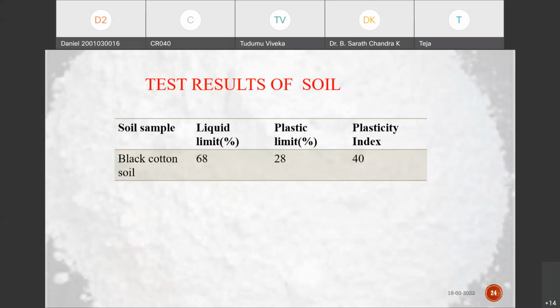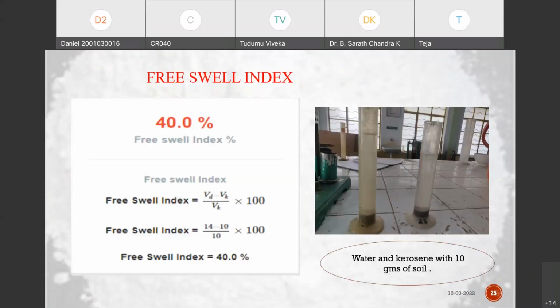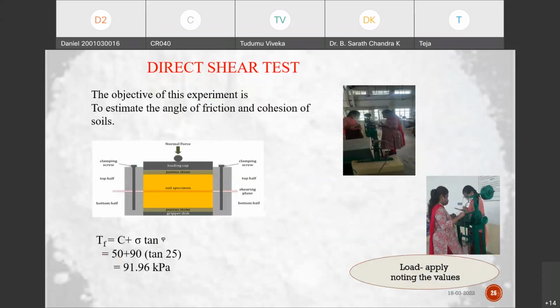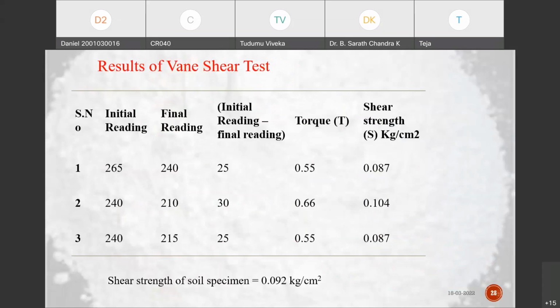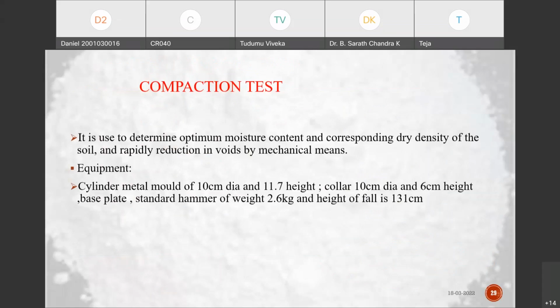For the soil, the liquid limit is 68%, the plastic limit is 28%, and the plasticity index is 40% for the black cotton soil. The free swell index is obtained as 40%. This is the direct shear test and the vane shear test. The shear strength of the soil specimen obtained from the vane shear test is 0.092 kg per centimeter square.